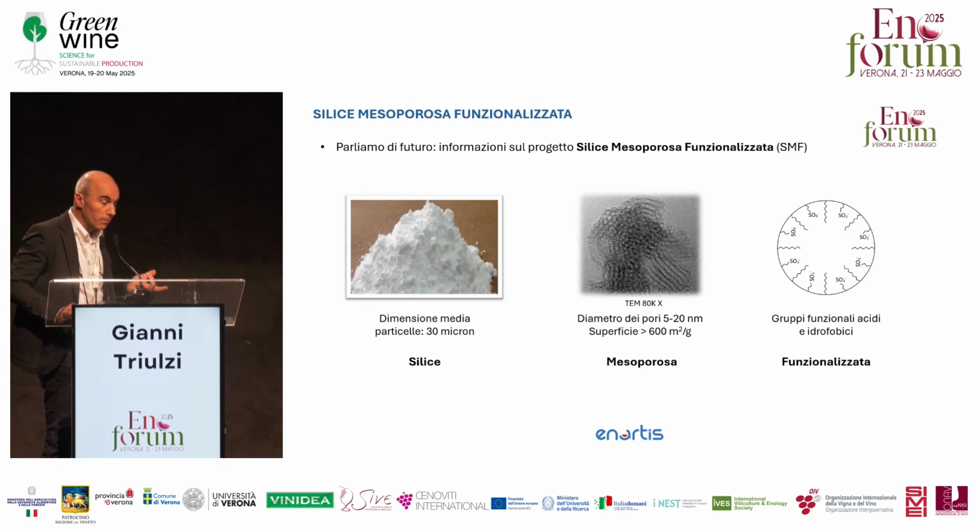They fall within two categories: acidic, with negative charges. Proteins are always positively charged at the pH of the wine, and then hydrophobic functions. You possibly remember earlier on when we talked about the hydrophobic areas of the molecules. So this makes this material highly specific in terms of protein stabilization.